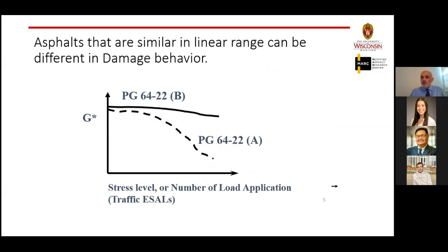Here are two PG binders. Both of them are exactly of the same grade, PG 64-22, probably the most widely used grade in North America. However, as you increase the stress and strain beyond the level of the specification, if you remember, we test unaged asphalt at 12% strain, we test RTFO binders at 10% strain, we test PAV binders at 1% strain.